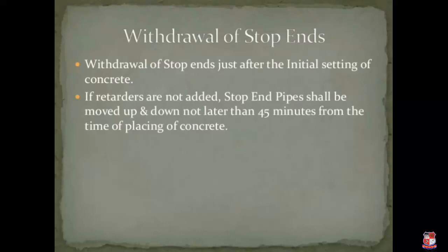Now, withdrawal of stop end. Withdrawal of stop end just after the initial setting of the concrete. If retarders are not added, stop end pipe shall be moved up and down not later than 45 minutes from the time of placing of concrete.